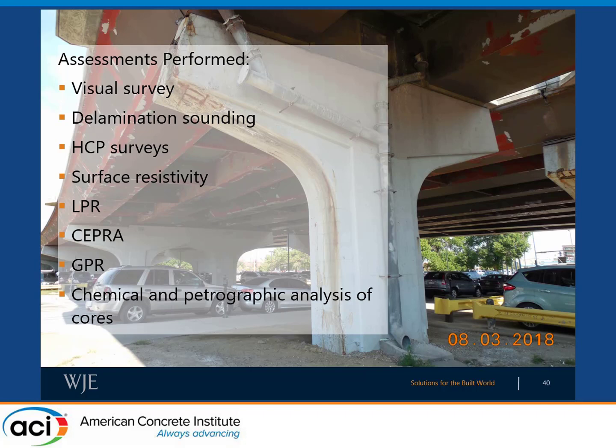And through this work, we were able to identify areas of these piers that had higher risk of corrosion than others. And so it helped us to go back, look at these piers at those locations where we were measuring high corrosion rates and high corrosion activity and figure out what's causing it. Is it an exposure issue, maybe a leak that's happening, something that might not be visible, perhaps the influence of a prior repair on the bridges, and so on. And so using all of these techniques, we were able to get a much bigger and broader picture of the current state of these bridge piers and make better informed decisions about how that material is going to degrade over the future.